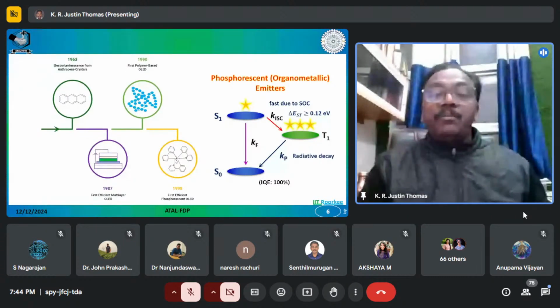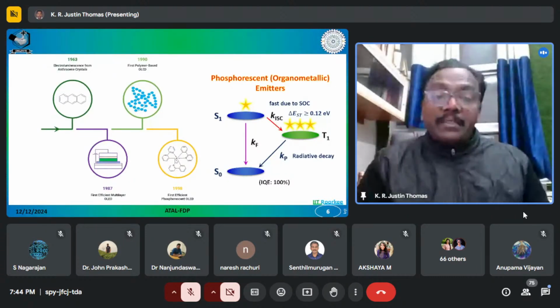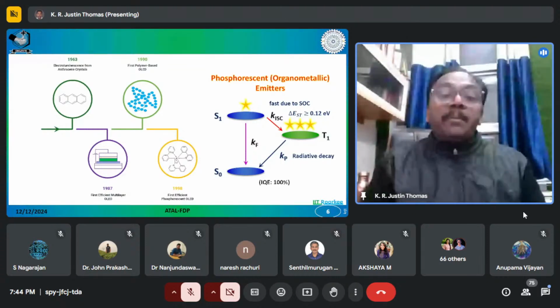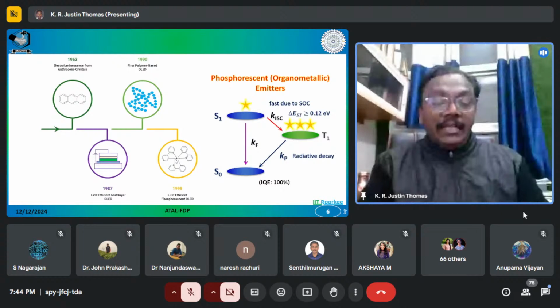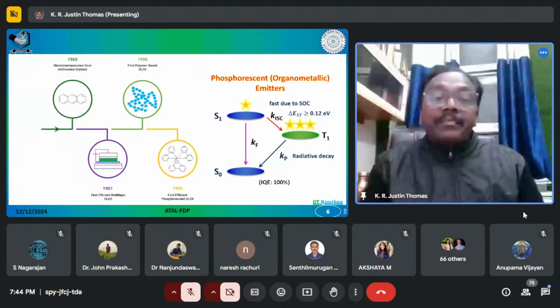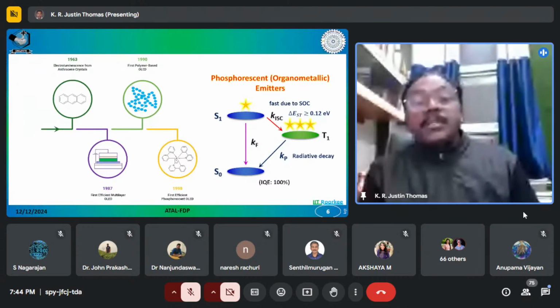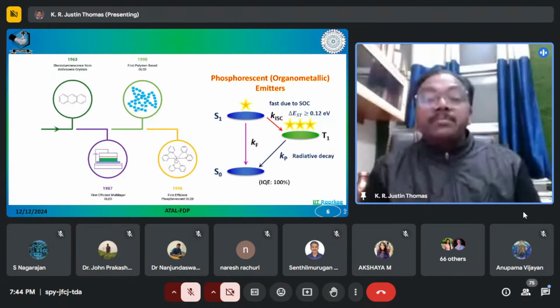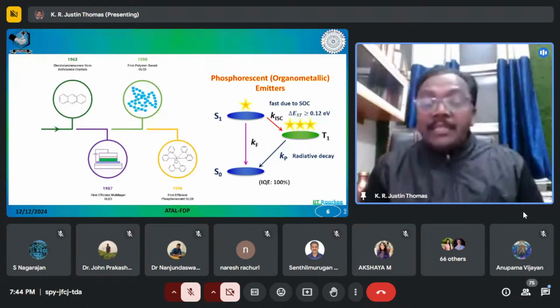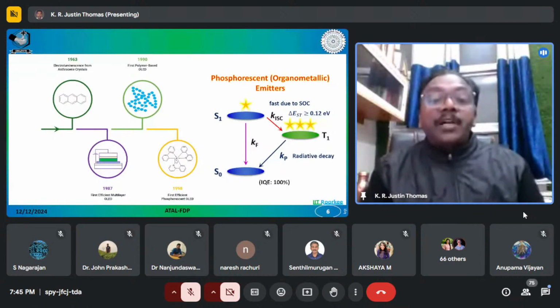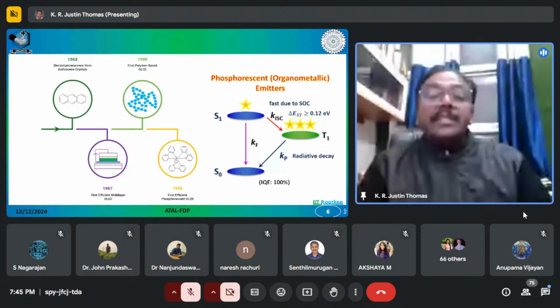Because phosphorescent materials have come, they can give internal quantum efficiency up to 100%. But there came a problem later. Most of these complexes are crystalline in nature. In order to have a very glassy thin film, which is necessary for a long-lasting LED, you need an amorphous material. But these inorganic molecules are crystalline in nature, so they don't have amorphous properties. That is the first problem. So you cannot use this molecule as such in the device. You have to use this molecule as a dopant in some matrix, which is amorphous in nature.